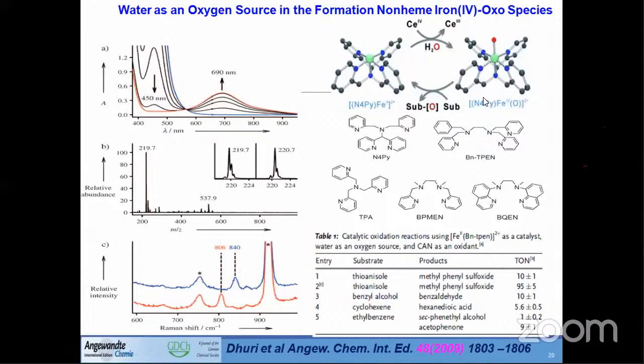Then we wanted to check whether this reaction is applicable to only one ligand, or to many ligands, because iron-oxo species were already reported with these ligands when I was working in those days. Of course, they were not reported in water. So I thought I would try to generate iron-oxo species using water as an oxygen source, with iron compounds stabilized by different ligands. Fortunately, we observed that these are the ligands. All five ligands give iron-oxo species in water.